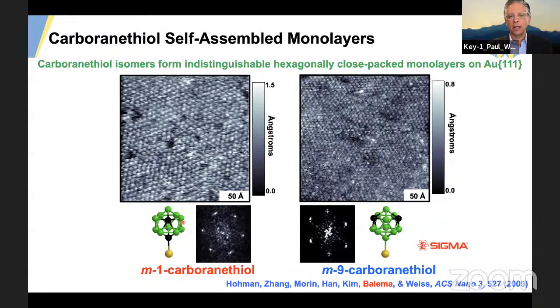So these are boron cages with 2 carbon atoms. And unlike what we teach in high school chemistry, the carbon here is behaving like boron. So each carbon atom has 6 bonds instead of what we normally think of as the maximum of 4, and that's because it's behaving like boron. I haven't shown all the hydrogens on here, but each atom has a hydrogen. And since carbon has 6 bonds, it's electron deficient, and wherever the carbon atoms are on the cage, that's where the positive dipole points.